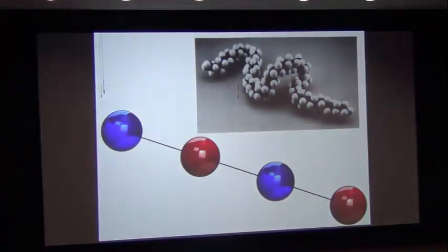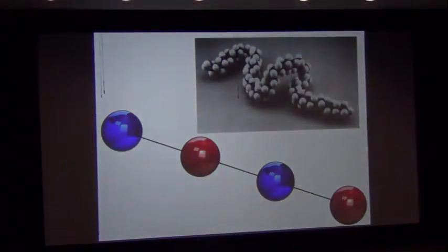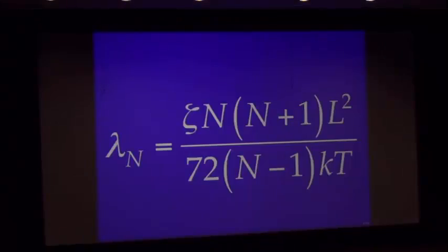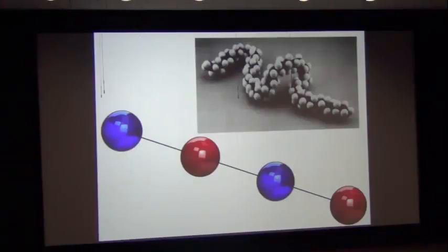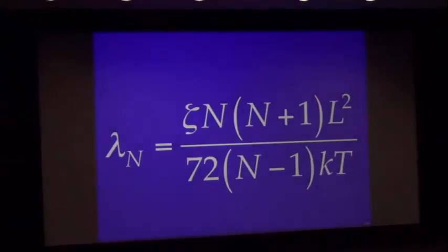You really should have distributed the beads along a line. For instance, this looks more like a molecule. But here's the thing. You can do that, and when you simplify the orientation distribution function, the lambda, you see, is still just a constant. It depends on the number of beads you distributed along the shish kebab, okay? But it's still just a constant. So everything I taught you about today is qualitatively the same as you would get for a shish kebab.